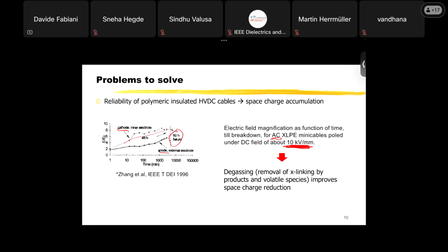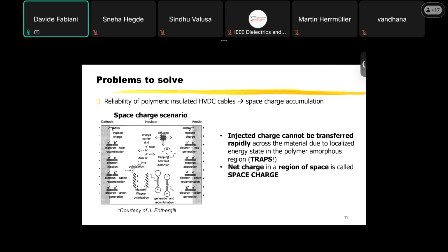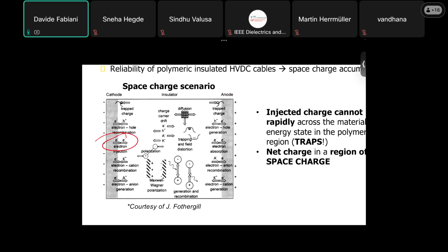The problem regarding space charge accumulation is that when you apply a DC field to a solid electrical insulation, you can have a lot of activities inside the insulation. In particular, you can have injection of charge from both the cathode and the anode. So you can have injection of negative charge or positive charge from cathode and anode respectively, or you can have dissociation of electric species inside the material, like I told you before, the cross-linking byproducts, the volatiles, that were inside the material, they could dissociate and create ionic charges that can then move inside the material.